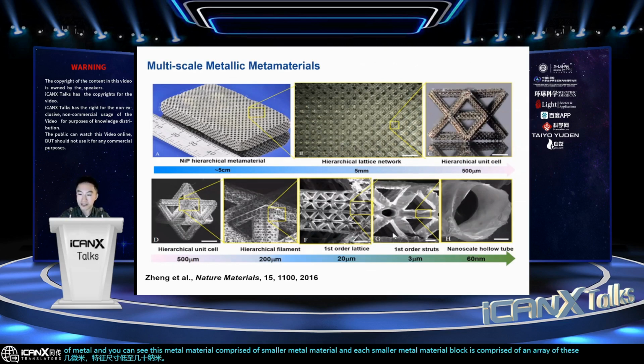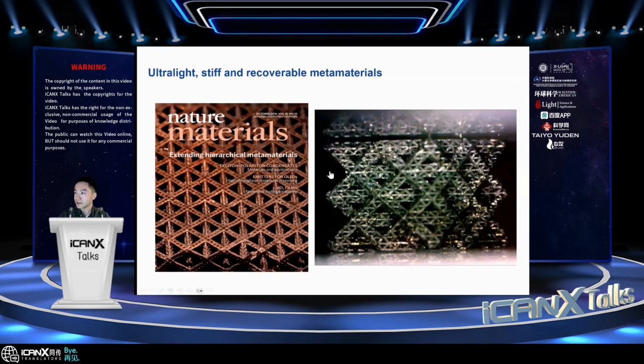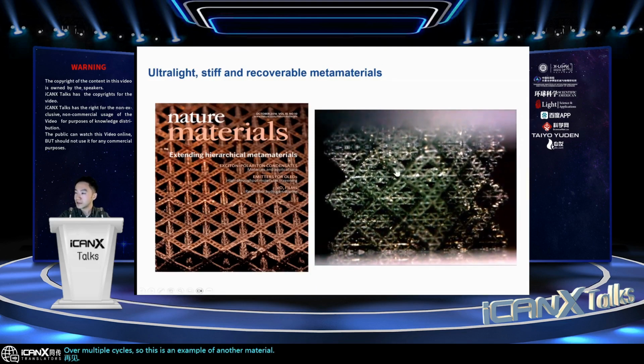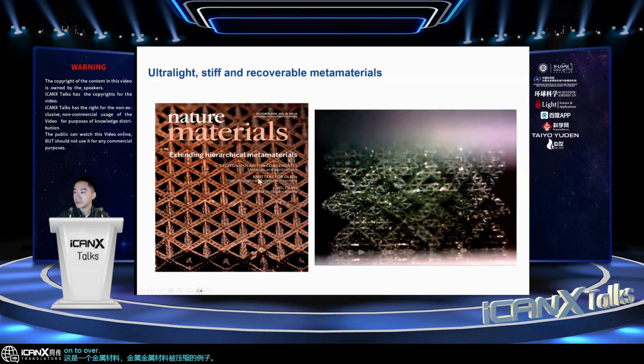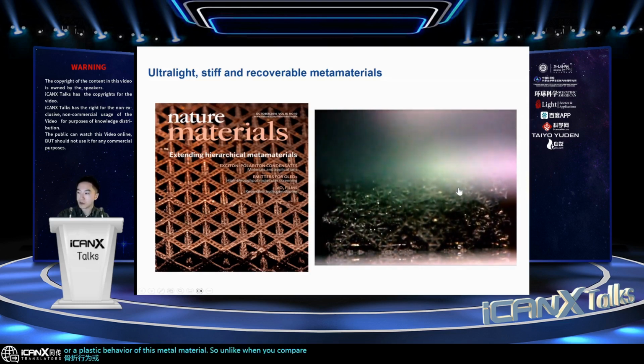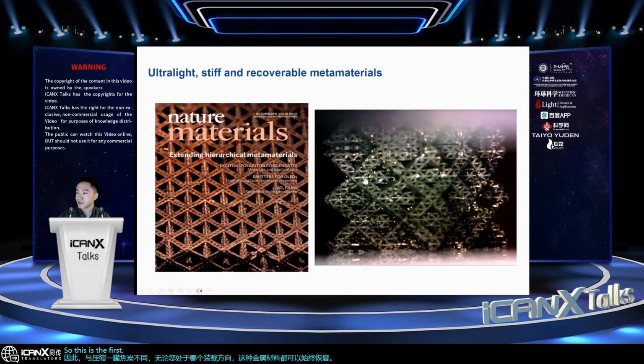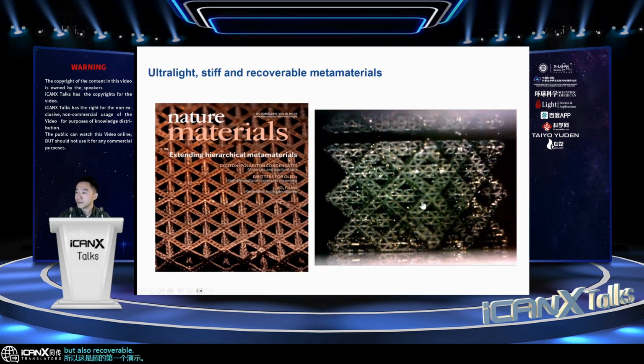So that really collectively gives you not only rigidity, but also high recoverability over multiple cycles. This is an example of a metallic metamaterial being compressed to over 90% strain, and you don't really see any structural failure or plastic behavior of this metamaterial. Unlike when you compress a can of Coke, this metamaterial can always recover no matter which loading direction you give the force. This is the first demonstration of an ultra stiff but also recoverable metallic metamaterial. This is really attributed to a collection of stretch dominated design over multiple length scales, and you can actually trigger different buckling loads at different length scales.